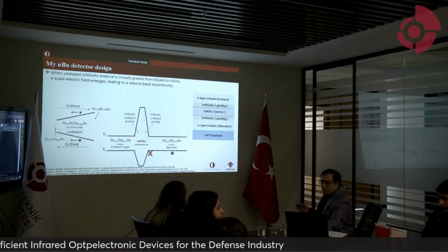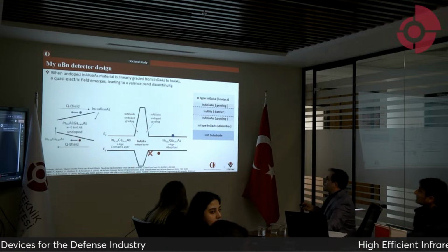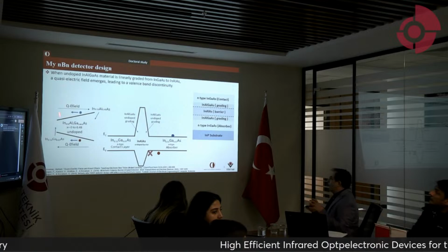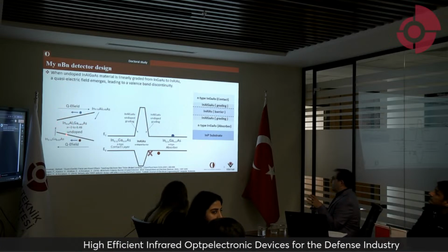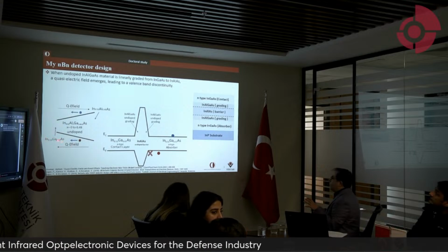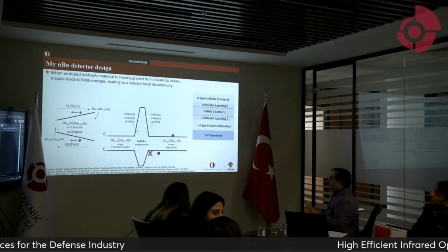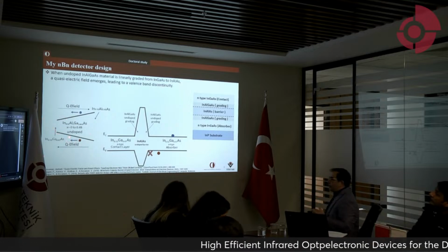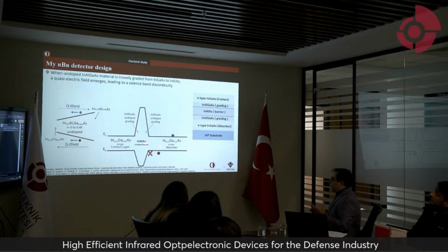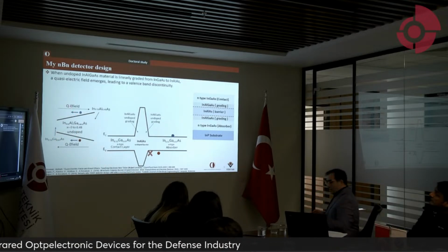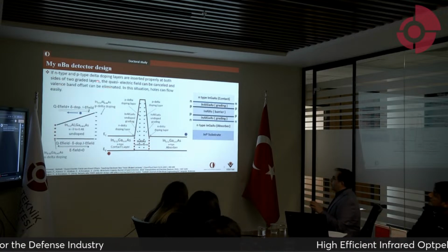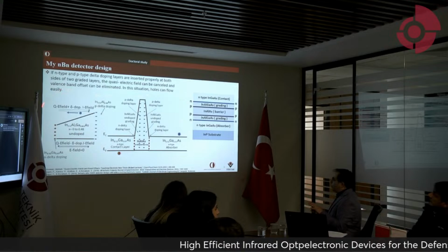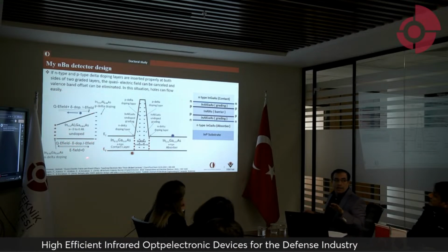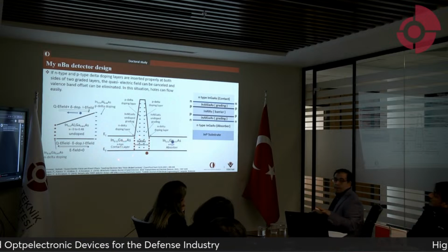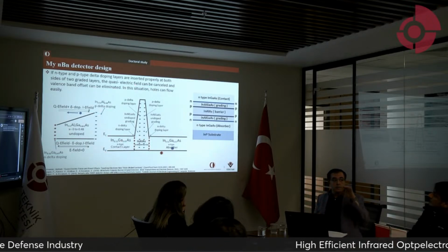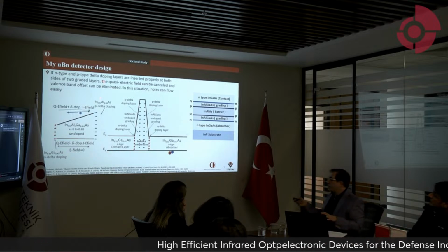But if you, for example, grade the layer, when it is linearly graded from indium gallium arsenide to indium aluminum arsenide, naturally a quasi-electric field emerges. Because of the quasi-electric field, this valence band discontinuity emerges. If N-type and P-type delta doping layers are inserted properly on both sides of these layers, you can cancel this electric field. And it means you can cancel this valence band. And this structure normally you can apply to the type 1 material systems. Now you can apply using these techniques.